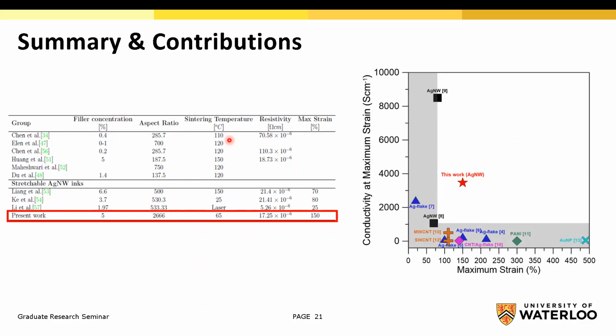And you can see they have a sintering temperature usually around 120 to 150. We have a much lower sintering temperature at 65 degrees. We have a really good, really low resistivity, and more importantly, while other state-of-the-art silver nanowire inks can tolerate 70 and 80% maximum strain, our ink can tolerate 150%.